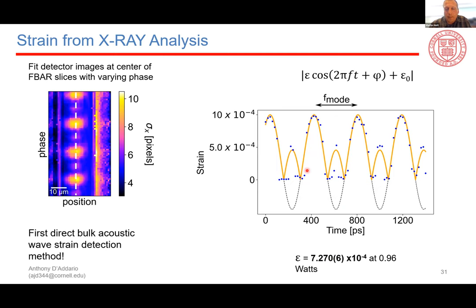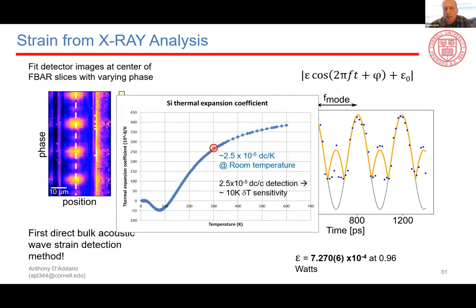And this is interesting because I think this bridges nicely into looking at semiconductors, not in terms of acoustics, but in terms of heat. If you think about the thermal expansion coefficient and what to expect for changes in temperature, with a detection sensitivity or limit around 10⁻⁵, you can think about imaging heat at about a 10 Kelvin change with a 20 nanometer beam. That's not great for a lot of things, but there are device structures like bipolar transistors that are quite a bit faster but generate a lot more heat, or on-chip photonics that receive a lot of optical energy in a very localized area, where the operating temperatures are quite a bit above what one would expect. How to mitigate that and how to separate these components out, we can answer that question in real space, in the limit that nothing else is going on, like piezo response or other electrically induced strain. Anyway, just food for thought.